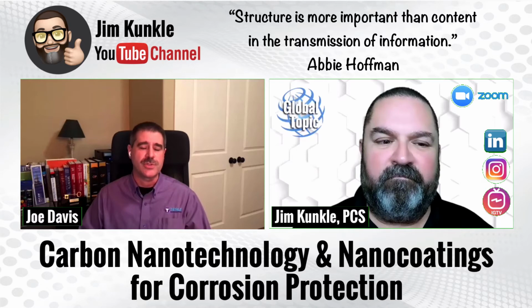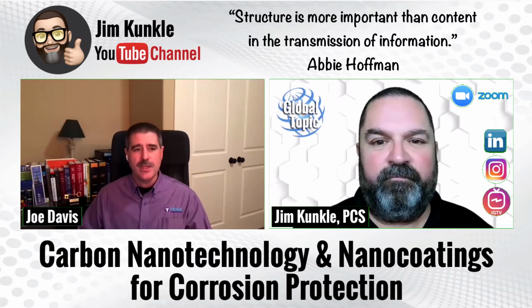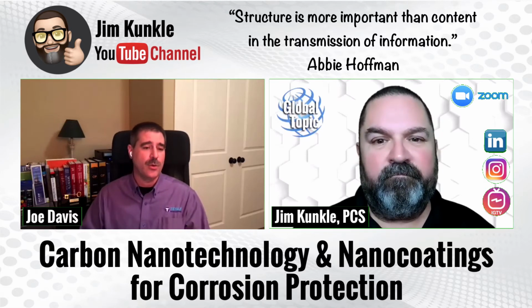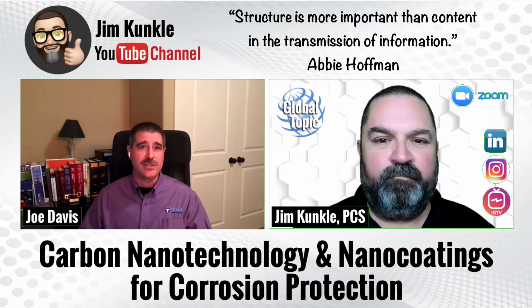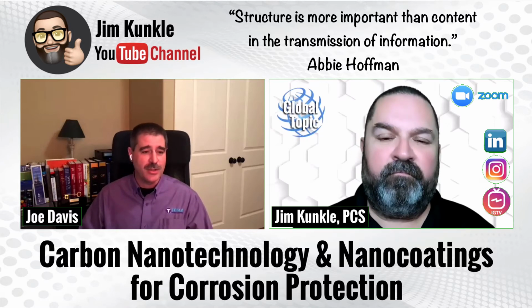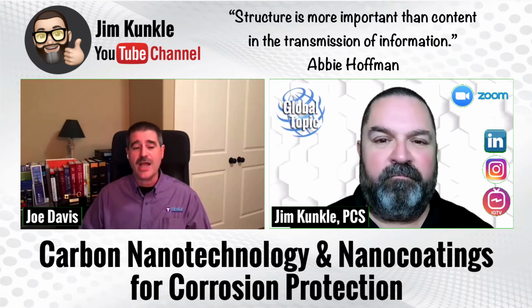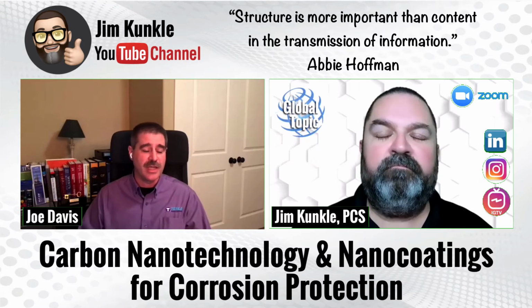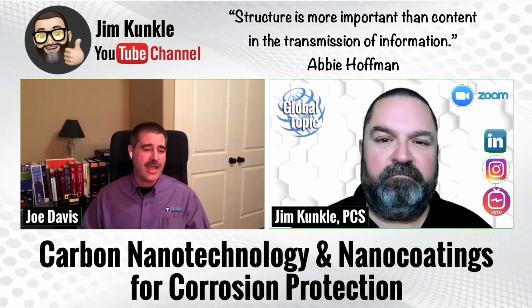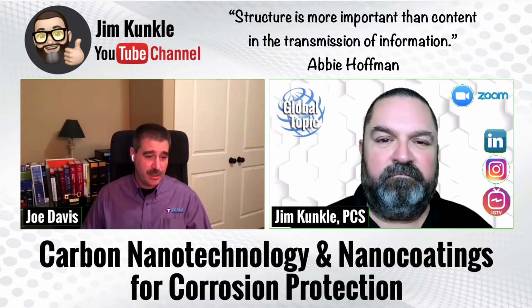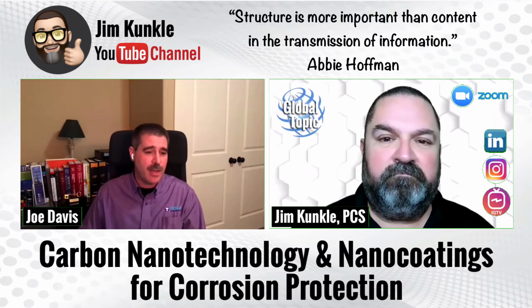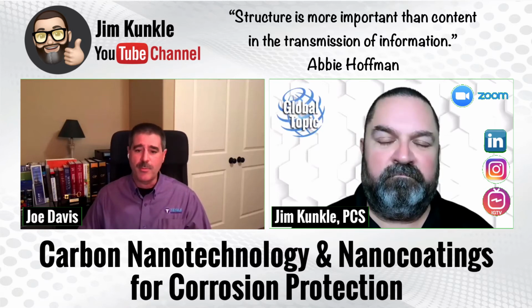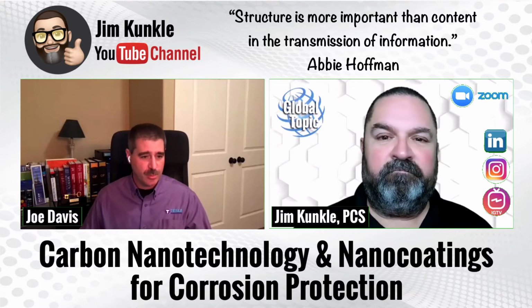And so what that does for us is a traditional zinc-rich coating is going to rely on metal to metal, the zinc as well as the zinc to the steel contact in order to transfer an electron. And as the zinc oxidizes, which is what it's designed to do, it actually insulates itself. And so that process is interrupted and you have no conductivity. What's different with our quantum network is that I can take an electron that can be donated by zinc anywhere on the matrix. I could be 3 feet away if I needed, and I could pull an electron down that complete quantum network and deposit it at the damaged area. So we really take advantage of those properties and get a real, true, sustainable cathodic protection.